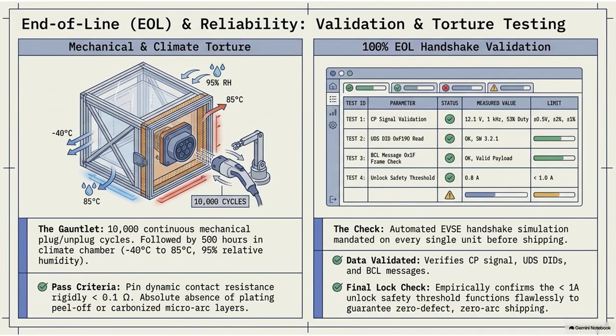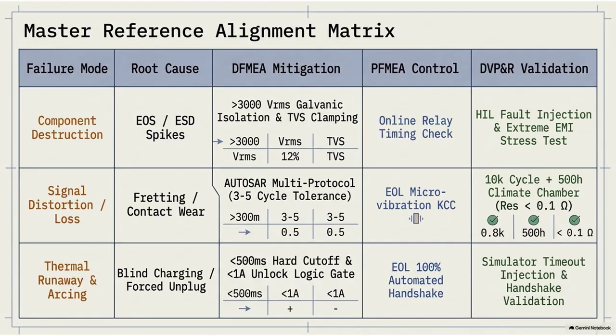And they do this while injecting 95% relative humidity into the chamber. They're creating the ultimate environment for galvanic corrosion and oxidation. The massive temperature swings cause the disparate metals in the port to expand and contract at different rates, forcing moisture deep into the microcracks of the worn pins. And they leave it baking in that 85-degree, 95% humidity sauna for 500 hours straight, almost 3 weeks of continuous chemical torture on a mechanically destroyed plug.